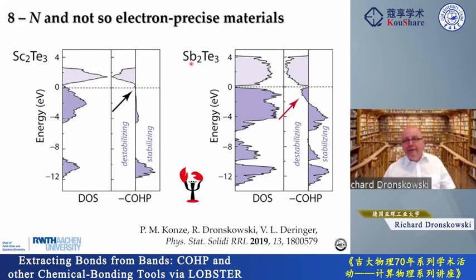It's different for antimony 2 tellurium 3 because this is from main group 5. So if this is trivalent, and it is trivalent, it still has 2 more electrons, 2 additional electrons. This material is in conflict with the 8-N rule. And you can see this because these are the 2 leftover electrons, which you usually would call lone pair electrons. But they are not alone. They show up as antibonding levels in the upper part of the valence band. It's very typical.